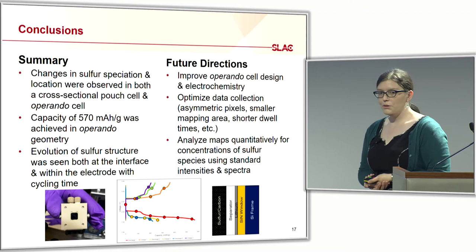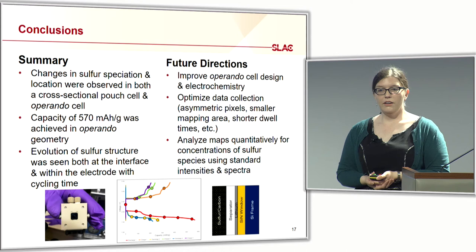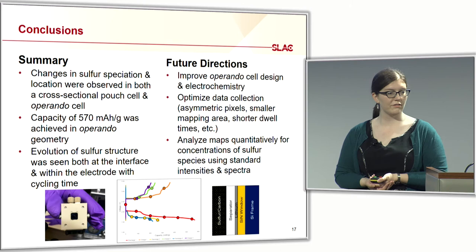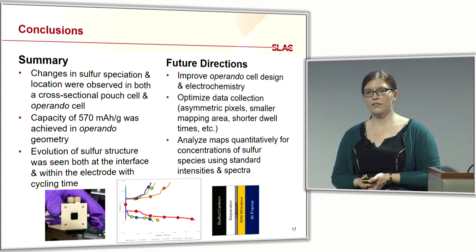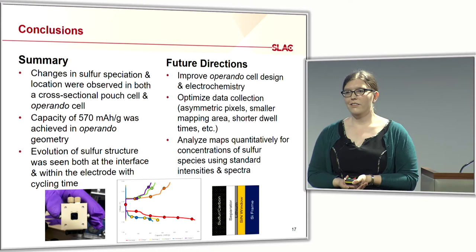In conclusion, I was able to observe changes in sulfur speciation in a cross-sectional pouch cell and an operando in-situ cell. I achieved a capacity of 570 mAh per gram sulfur in the operando geometry, and I was able to see evolution of the structure both in the electrode and in the diffusion at the interface.